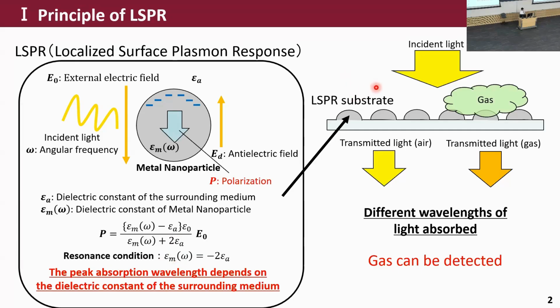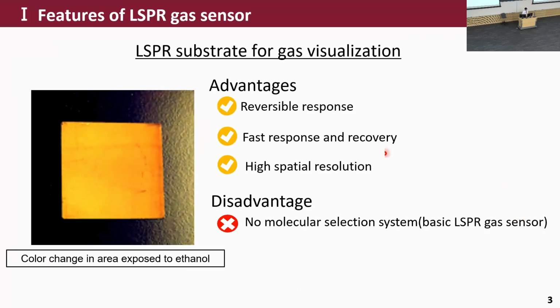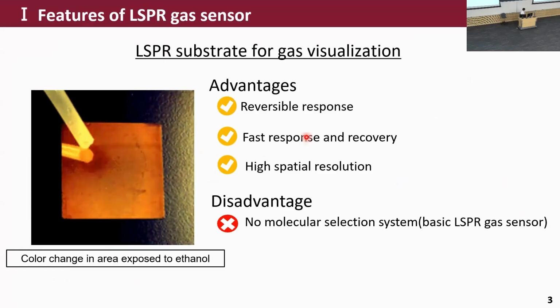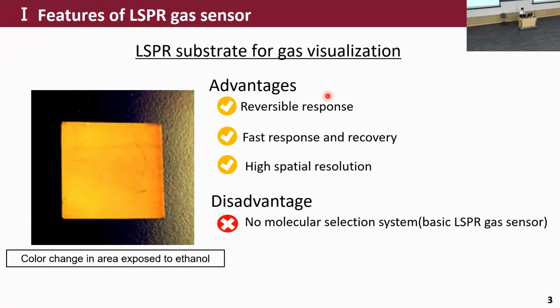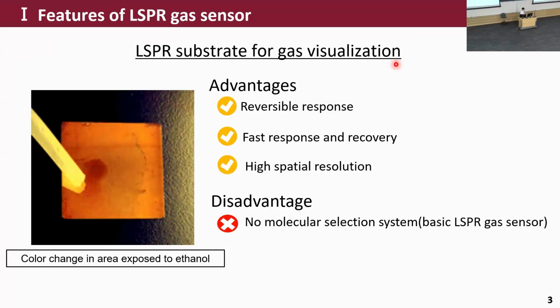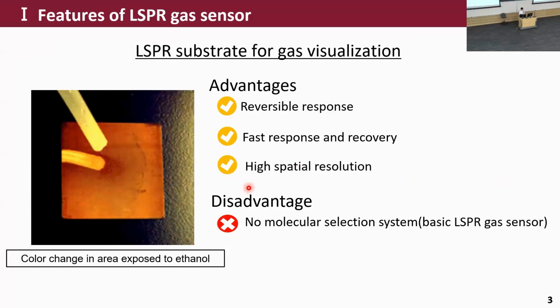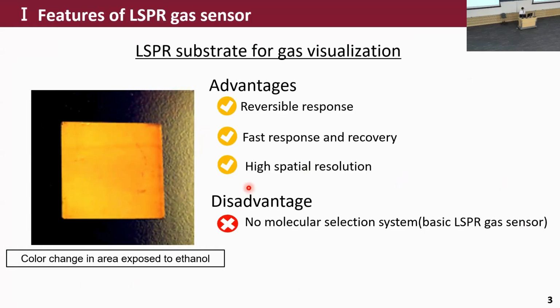As shown in the right figure, when incident light is irradiated onto the LSPR substrate, which is an aggregate of metallic nanoparticles, the peak wavelengths of absorbed light are different for light passing through air and light passing through gas. As a result, the gas can be detected as a change in optical properties. This is an LSPR substrate. The color changes in the area exposed to ethanol gas. Advantages are reversible response, fast response and recovery, and high spatial resolution. But the sensor does not have a molecular selection system, basically.